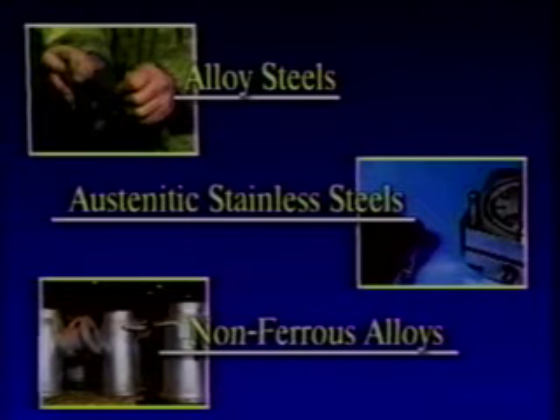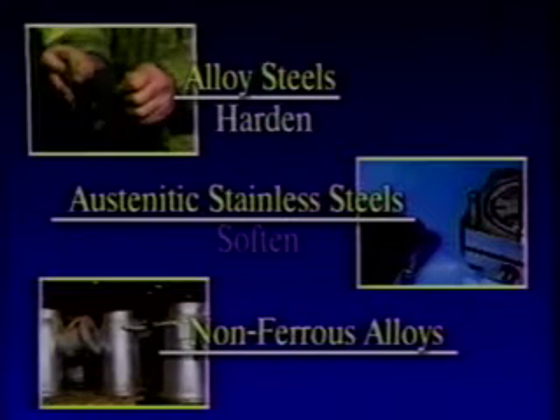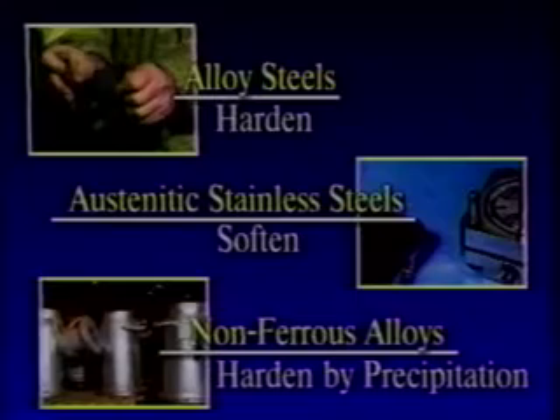To summarize, quenching carbon steels, tool steels, and alloy steels leads to hardening. Quenching austenitic stainless steel prevents the loss of corrosion resistance while retaining the ductility and toughness of the material, which is another way of saying it retains its softness. And quenching leaves non-ferrous alloys in a soft condition, ready for hardening by precipitation.